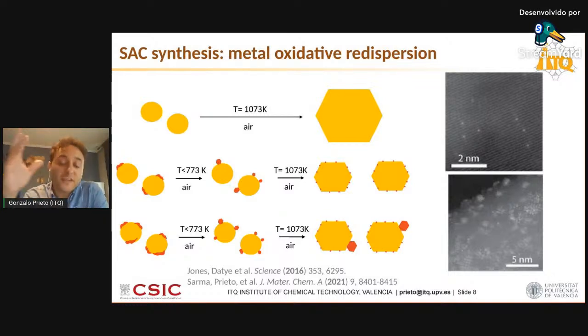This stabilization of single atoms happens to a certain limit, and the limit is dictated by the saturation of the anchoring sites of the support. The surplus of metal that we try to disperse in there will end up, in most cases, agglomerated, forming oxide clusters or nanoparticles. That's the bottom part of the cartoon and the bottom micrograph on the right-hand side.